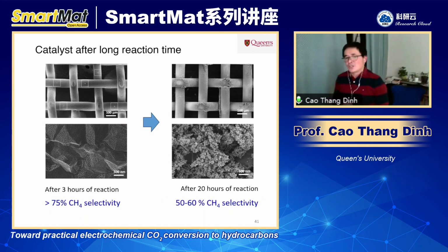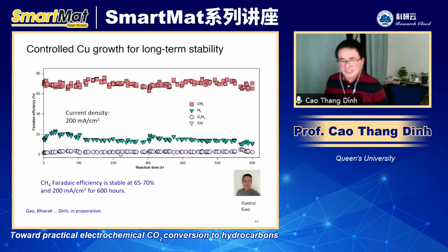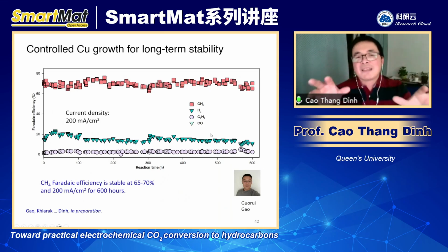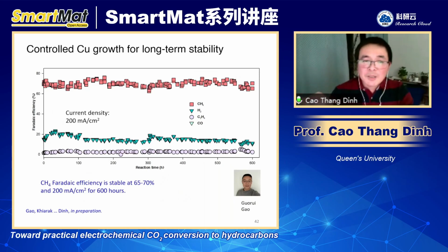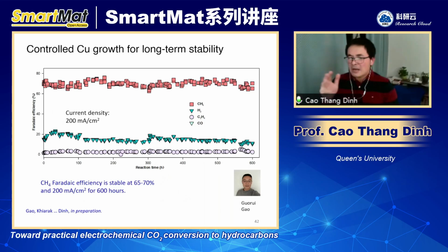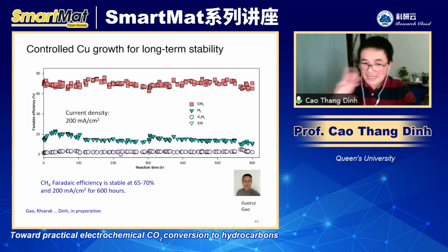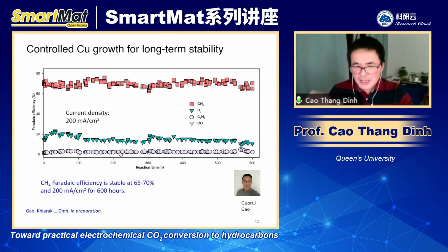And that is one of the challenges that our group is now focusing on: how do we control the growth of the copper? I cannot tell you exactly how we are doing that, but we are confident that we can control the growth of the copper so that we can keep high methane selectivity. And that is the ongoing work from Fei, who found a way to stabilize the growth of the copper. And now we can keep the reaction running for 600 hours, keeping the selectivity around 70%. Right? So we go from 10 to 12 hours now up to 600 hours, and hopefully we can extend it further based on the strategy we are developing right now.